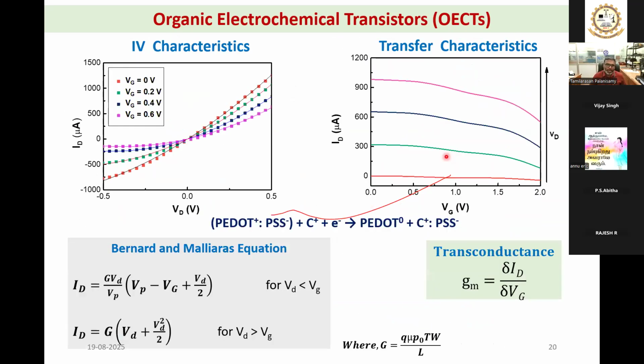Okay. So now we have created an OECT with this microfiber cylindrical channel, and we tested its IV characteristics. Generally, the IV characteristics for an ohmic device will be a straight line, something like this. And if you see your OFET or FET, you will see a linear region and then a saturation region called the pinch-off region. But in this case, if you see, the profile itself is something crazy. It is not a linear profile. And this is not the first time we observed this. It is already observed and well known for OECTs, not for other transistors.